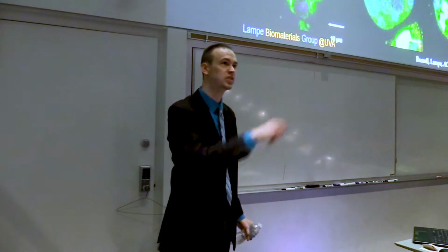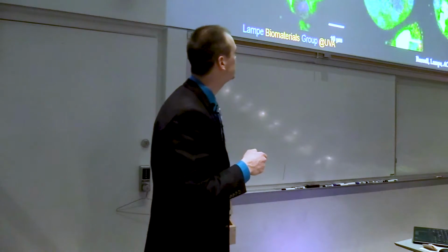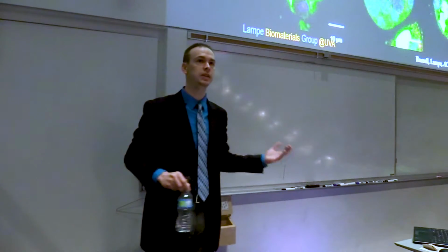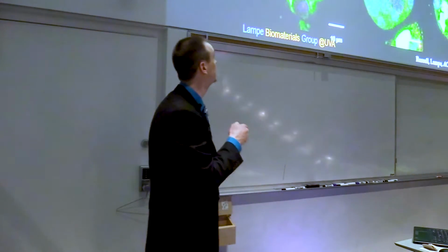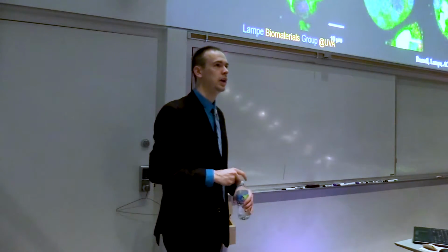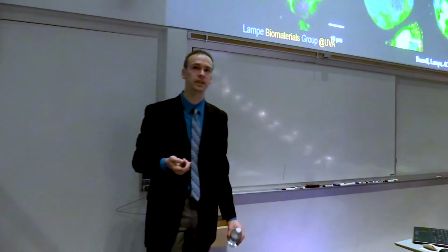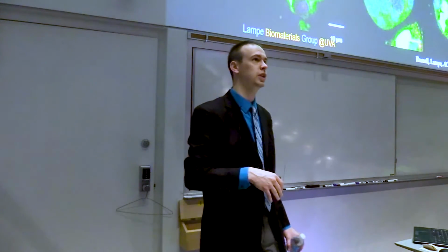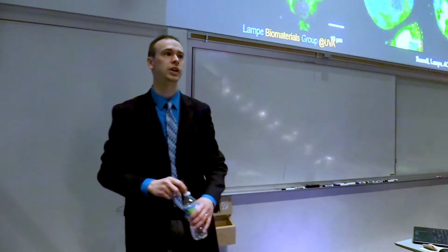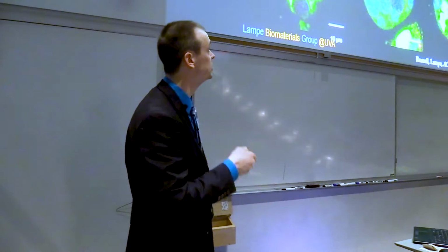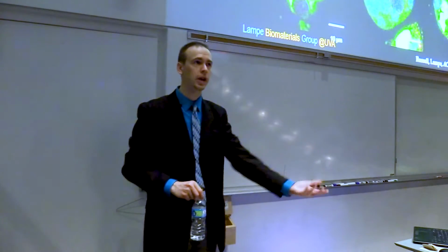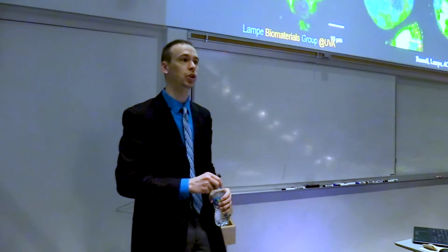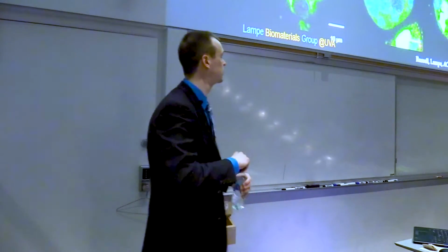This should be a membrane stain. It sticks around the outside of the cell, right? And we see that present in these 2 conditions, but not over here, right? So we don't see very much of this stain for PDGFR alpha in the context of this least stiff hydrogel. So what we actually think is happening here is that cells in this very soft, very compliant hydrogel have started to actually de-differentiate and go back up the progenitor cell stream, whereas these cells are continuing to stay as oligodendrocyte progenitor cells and making more of themselves, but staying on that kind of pathway that we're looking for between neural stem cells and oligodendrocytes.